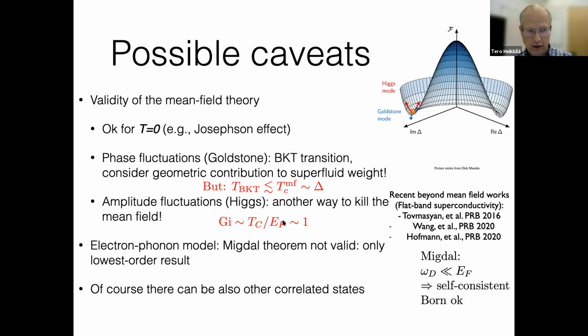If you're interested, I can talk a bit more about how we have estimated these amplitude fluctuations in the rhombohedral graphite. But I just mentioned that these are usually described by the so-called Ginzburg number, which is sort of proportional to the ratio between the critical temperature and Fermi energy, and in the flat band case, Fermi energy becomes small, so this can be of the order of unity.